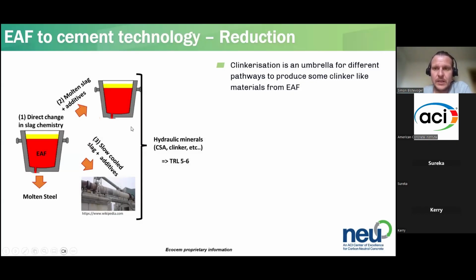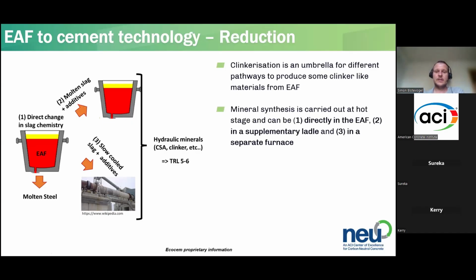The next one that is always in discussion is using EAF slags as a feedstock, either within an electric arc furnace or a more conventional clinker technologies to make some sort of clinker, maybe not Portland clinker, but other clinkers out of it. And there has been some research in there. The problem mostly is that you would need to re-put the energy for the clinkerization reduction into the material.